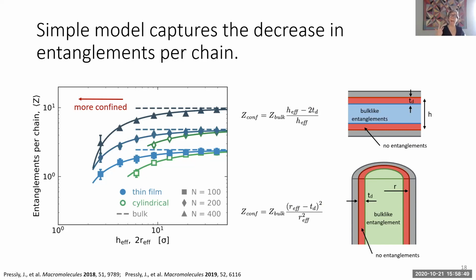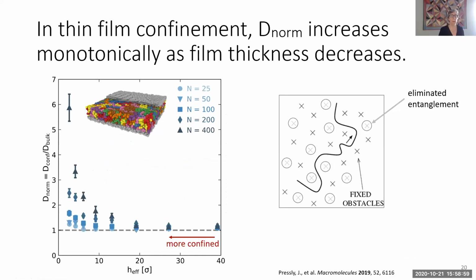Okay, so we can anticipate now that as we decrease the number of entanglements, we're actually going to increase the diffusion coefficient. And so that's what's shown here for the thin films. So as the film gets thinner and thinner, we can see the diffusion coefficient increases. And this increase in diffusion coefficient is more dramatic for the higher molecular weights because the drop off in entanglement density is larger at higher molecular weights, longer chains. Right? And so this is the schematic I showed you earlier, but now imagine that because it's confined, there are fewer entanglements. So I've kind of erased some of these entanglements, and that makes it easier for the polymer to diffuse.